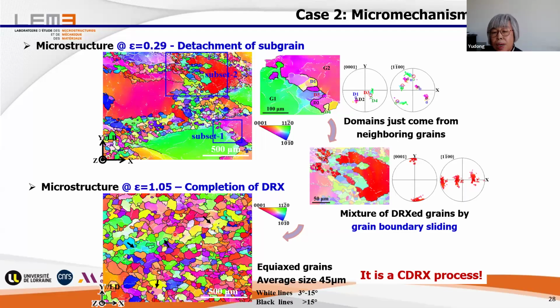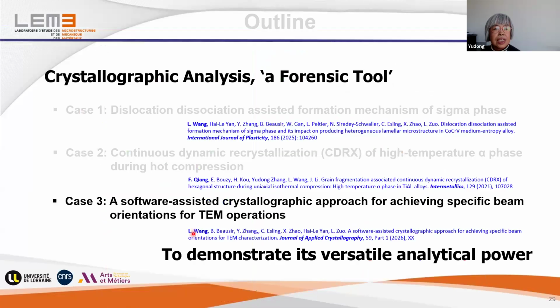Starting from stress-induced boundary migration, and then evolving by absorbing additional dislocations of different types with grain boundary sliding, and then from the grain boundary layers, zones, to the interior of the coarse grains. And this process repeated, until the completion of the recrystallization. So this is the second example.